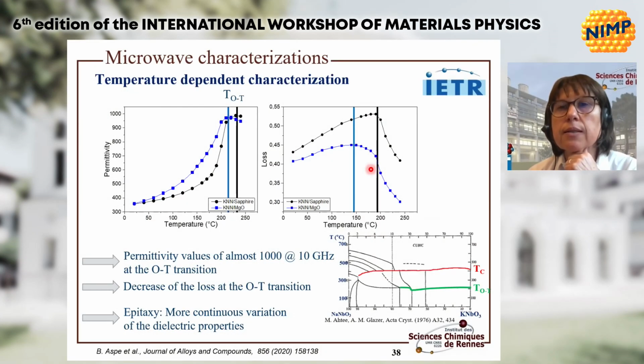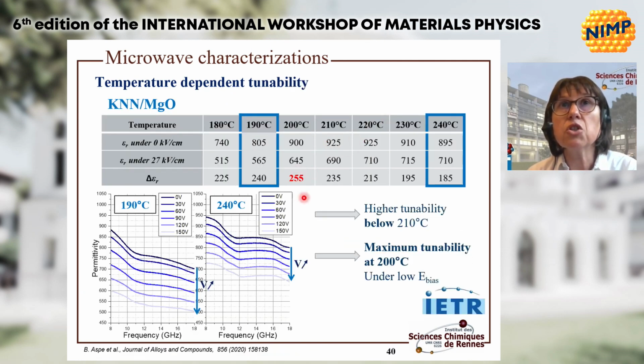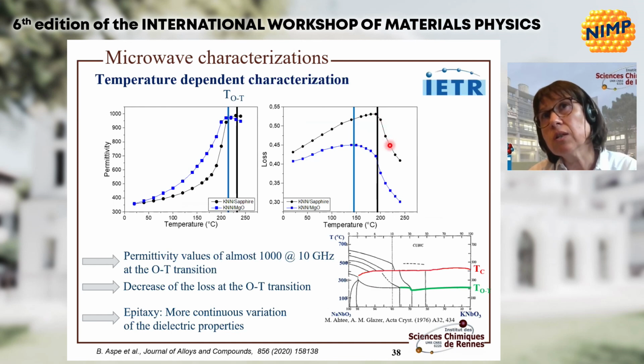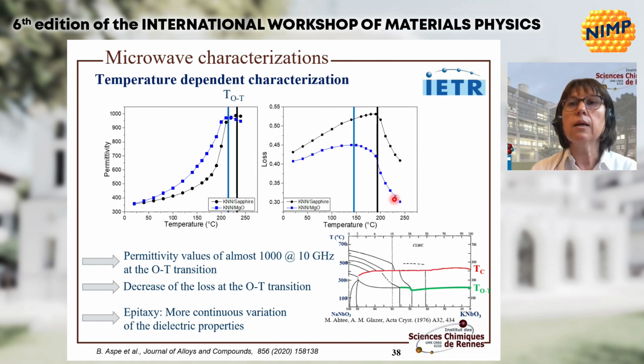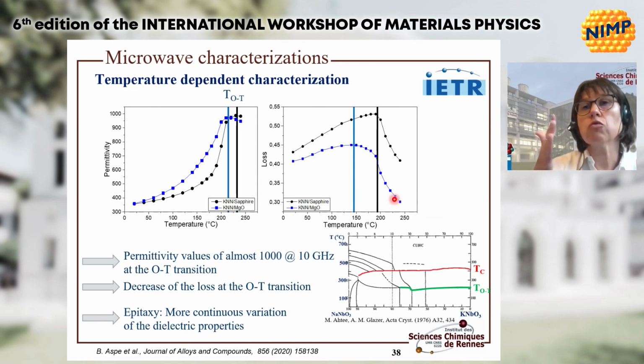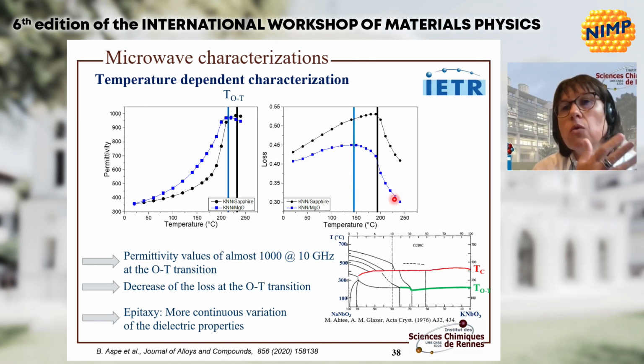If we have a look again at this graph, we can see what happens around 200 degrees. We can see that at this orthorhombic-tetragonal transition, the permittivity is higher, but the tunability itself is much higher. At the same time, we can see that just after the transition, losses are decreasing. Then I believe that this is a promising route to investigate: the possibility to change, either by strain or by the composition itself, this transition to shift it towards at least room temperature in order to save some losses.